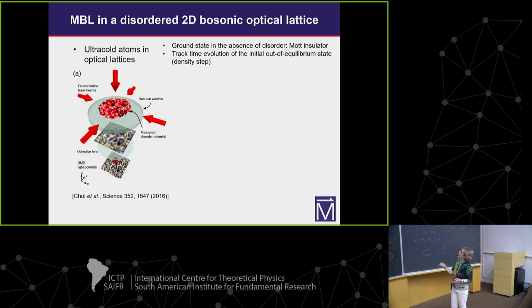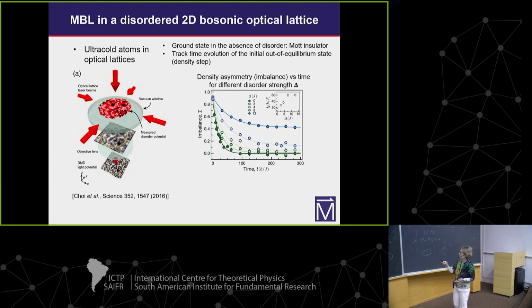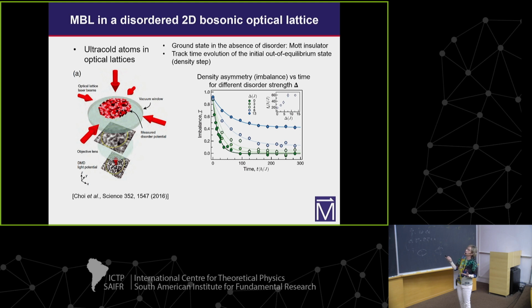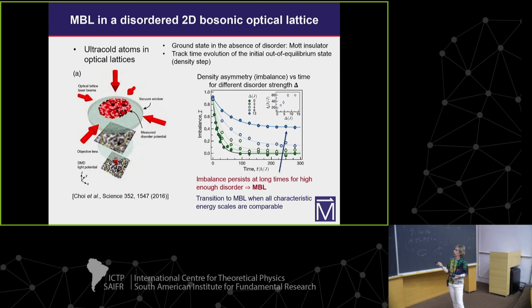So this is what they track, the density imbalance versus time, for different levels of disorder. Green points show the case when the disorder is zero — you can see this imbalance very quickly goes to zero, so all the atoms become uniformly distributed. But as they increase the disorder, there is some finite value above which the system, at least on these experimental time scales, doesn't go to zero. It persists at long times, and this was taken as evidence for many-body localization.